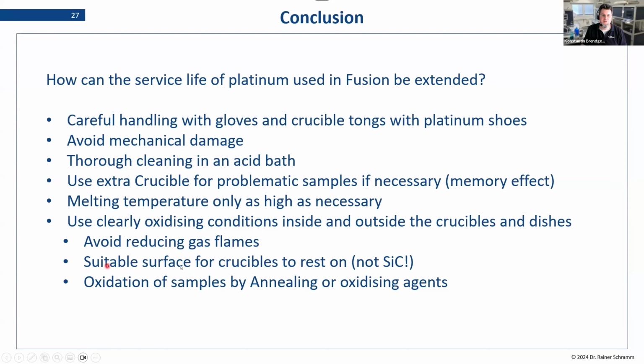There is a well-known history about people using silicon carbide as their surfaces for working. And also, in furnaces, they used silicon carbide resistors, basically. If they got in contact with platinum and you later heat that platinum, there was a very high chance of them destroying the surface. And in worst cases, they actually ate a hole straight through the platinum. So you want to be very careful with handling. And in terms of sample, oxidization is the key here. Get everything into an oxidic form, and then the danger of your platinum being damaged is very low.